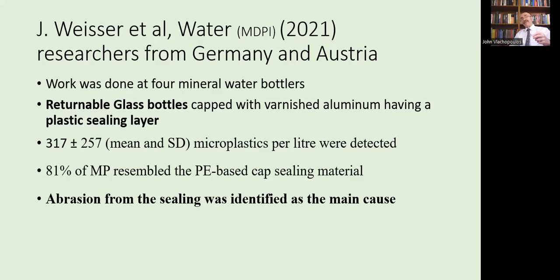Well, the glass bottles were capped with aluminum, but aluminum by itself provides no sealing. The sealing material was HDPE. And in fact, they say that 81% of the microplastics resembled the PE-based cap sealing material. And they identified abrasion during opening and closing as the main cause of the release of these microplastics.